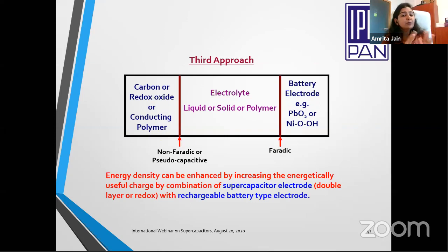Third approach, carbon or redox material or some kind of conducting polymer, and the other side can be a battery electrode, of course, sandwiched between electrolyte material. So energy density can be enhanced by increasing the energetically useful charge by combination of a supercapacitor electrode with a rechargeable battery type electrode. This is the most advanced stage capacitor, but it is not easy to do this combination. Looks quite easy, but it's not easy to find the fit materials which play together. But if we find a good material, then we will be able to achieve good energy and good power density, certainly.